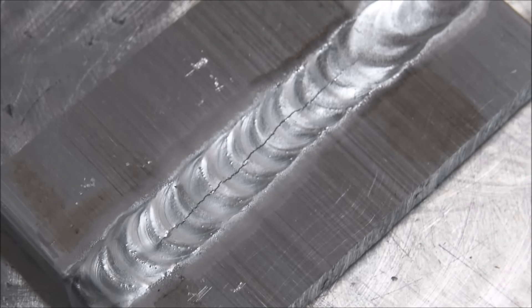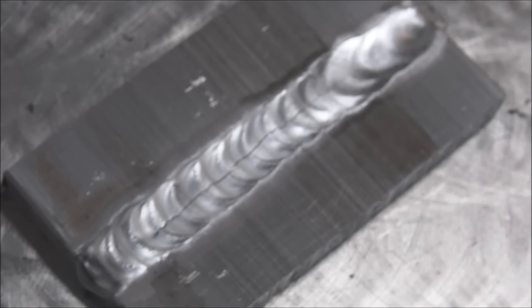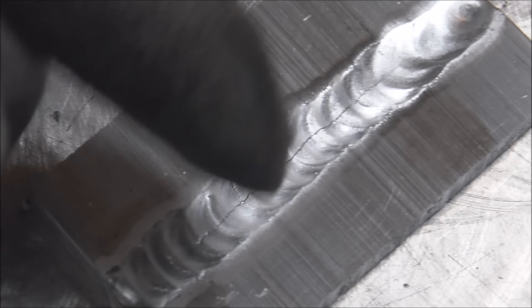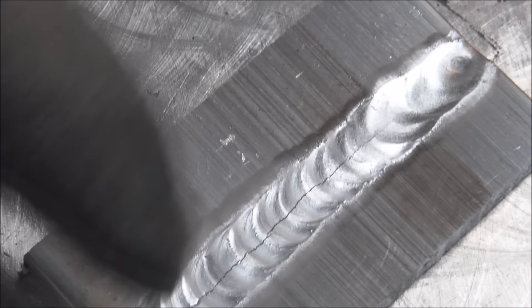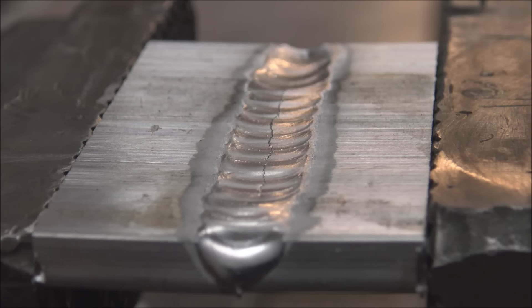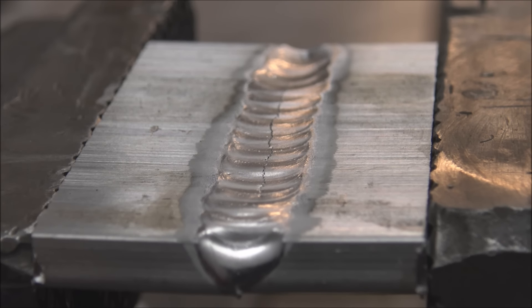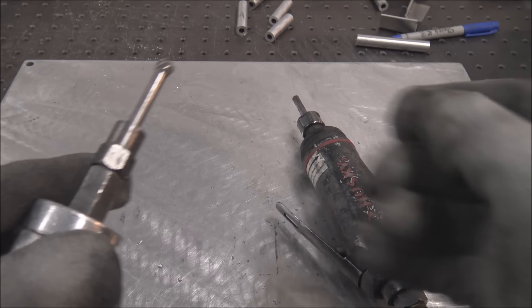So if any of you guys are wanting to get into doing some repair weld work, if you come across something like this, you want to bevel it out with a die grinder and get all that crack gone and then fill it back in.